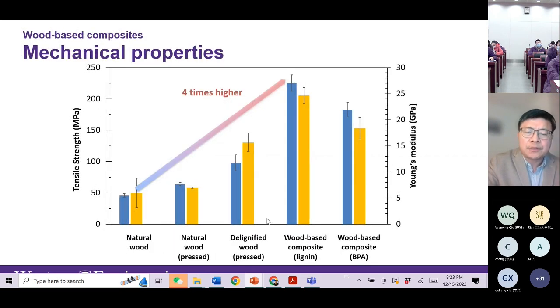Similar for tensile strength. Our material, shown here, has almost 4 times higher tensile strength compared with natural wood, and is also much stronger than the commercial epoxy resin-based composite. So this is another property demonstrated by this new material. Our lignin-based epoxy resin composite with wood achieved a much higher tensile strength and fracture strength.